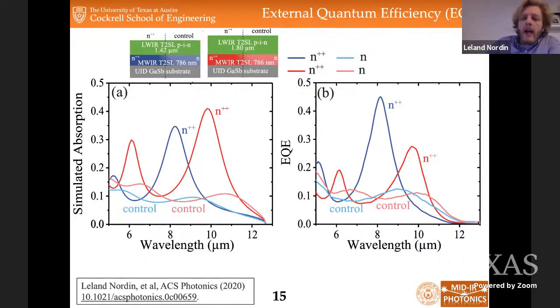And then our actual enhancement comes out to about 4.5-ish. We realized 45% EQE for the 8 micron target, where it's only 10% in the control, and then around 2.7 in the 10 micron target wavelength. And again, it's about 10% for the control, but about 27% for the N++ enhanced, or the doped, highly doped semiconductors.